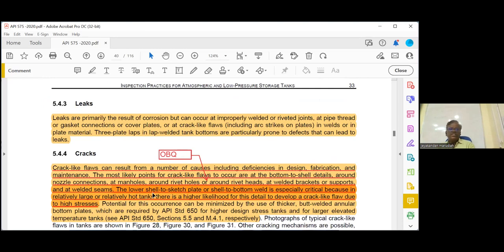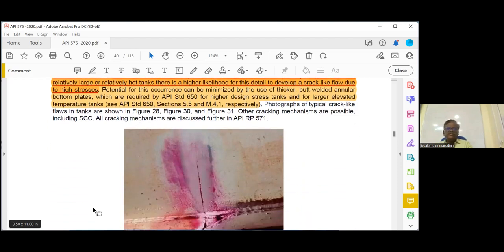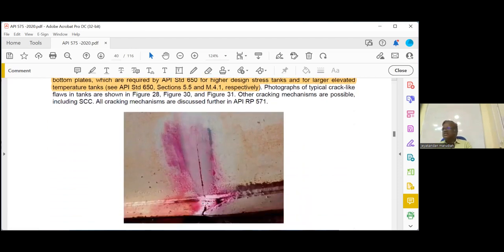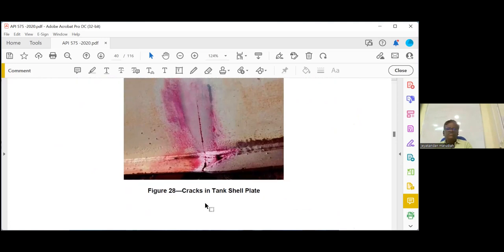The lower shell to sketch plate or shell to bottom weld is especially critical because in relatively large or hot tanks, there is a higher likelihood in this detail to develop crack-like flaws due to high stress. So the shell to bottom weld is highly critical. I told you, sketch plate means if you are not using an annular plate, it will have a higher thickness than the bottom plate. If you are using the same bottom plate to weld with the shell, that plate is called a sketch plate. So the shell to bottom weld crack is very dangerous. Immediately it should be repaired.